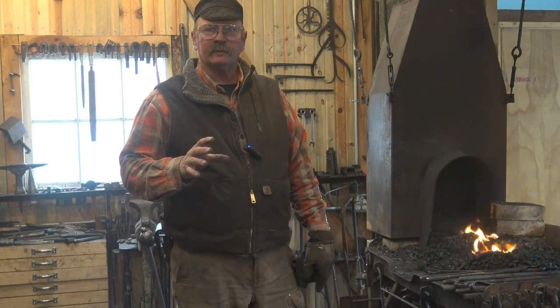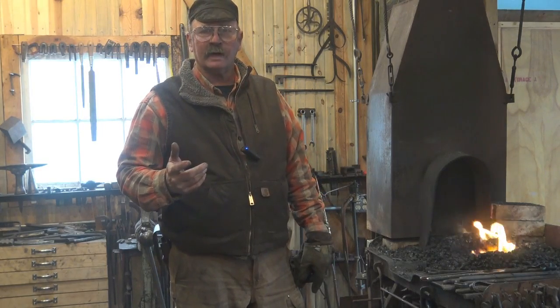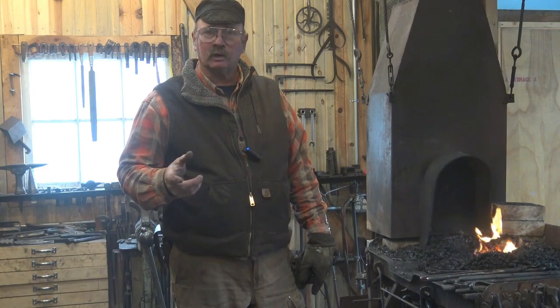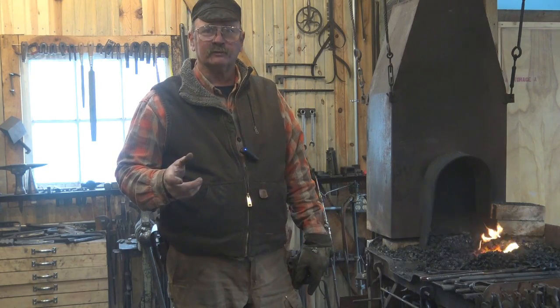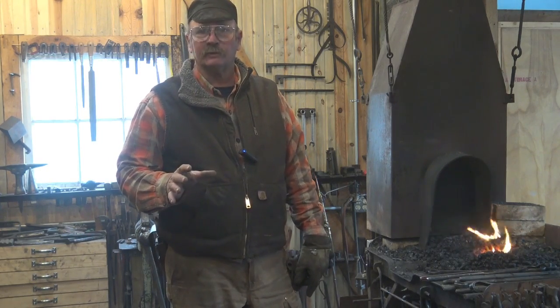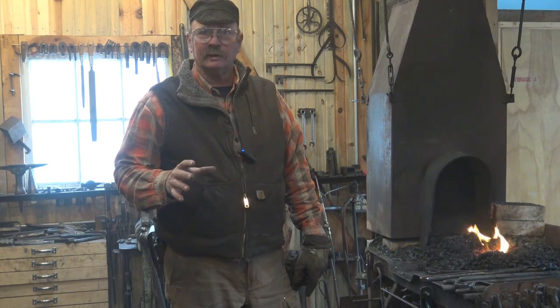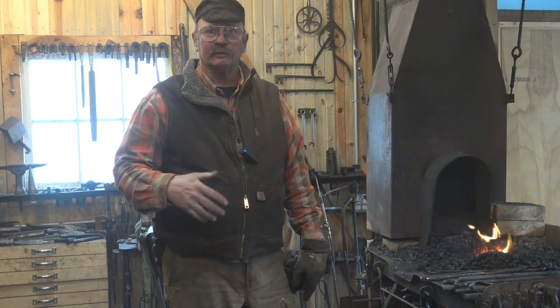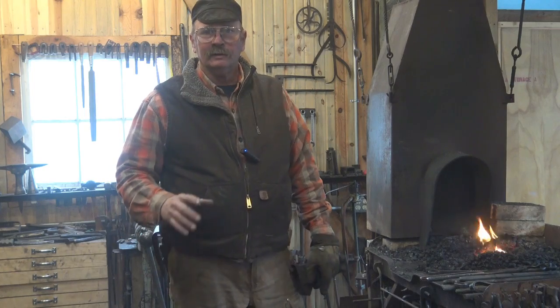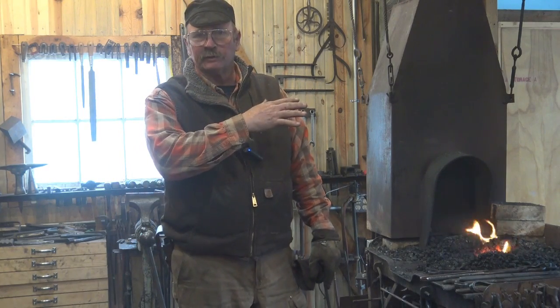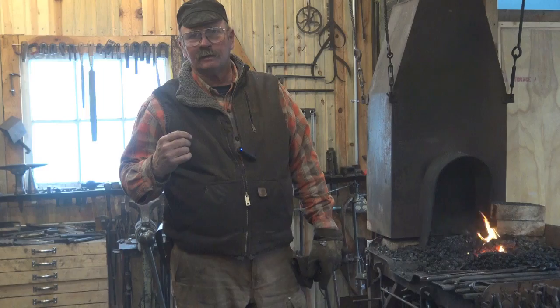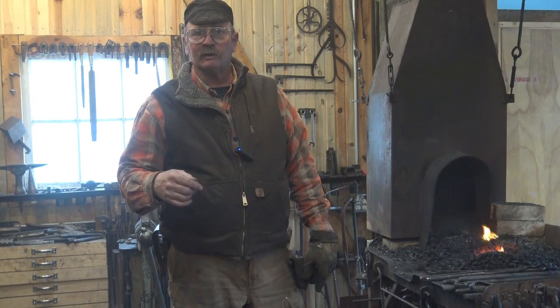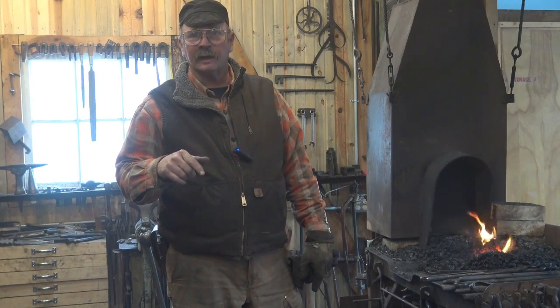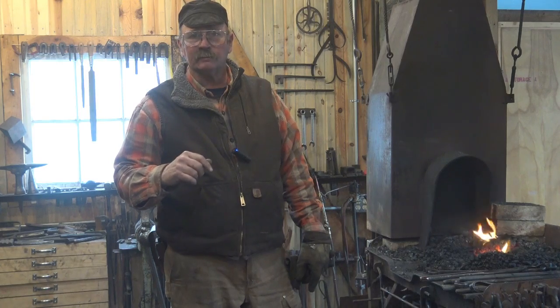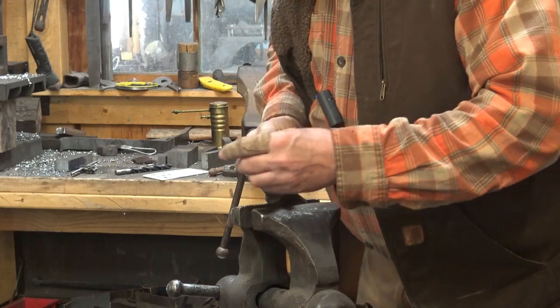We're going to let those temper in the toaster oven for an hour. That's a good time period. Check the charts and the tables and your other resources and see if they need something different than what I'm doing. Some steels like to be tempered at least twice, or they need to be tempered for 2 hours or whatever. But I'm pretty comfortable with this for these tools. So it's going to stay in there for an hour. I'm going to go have lunch, then we'll come back and we'll clean them up and sharpen them and see what we ended up with.